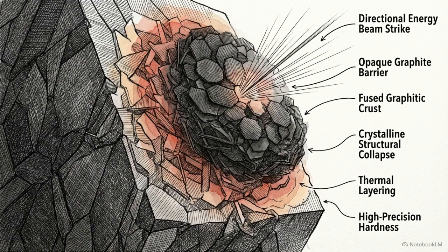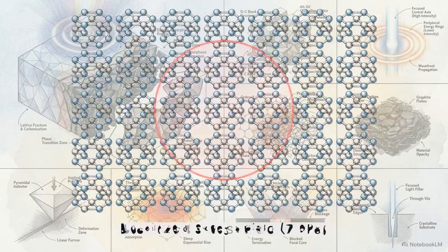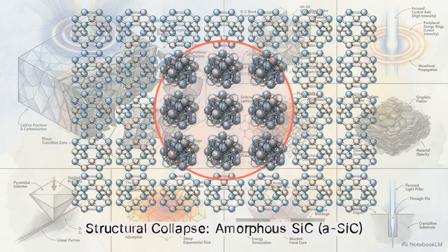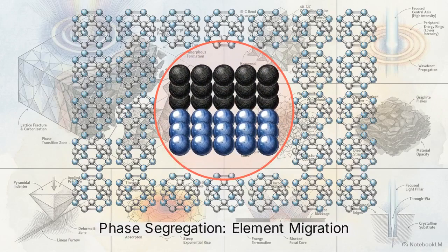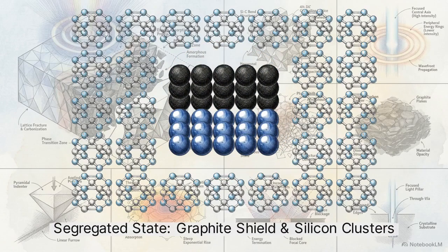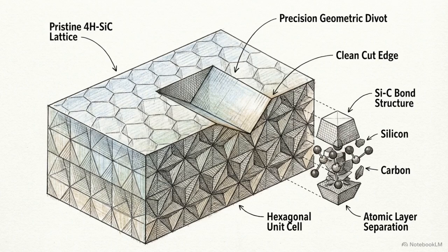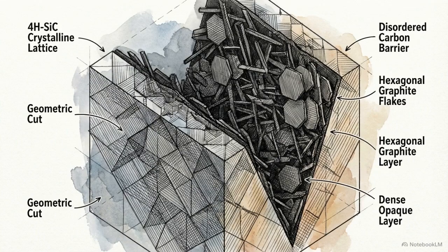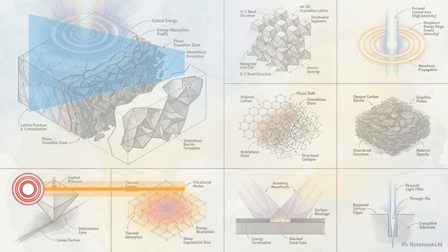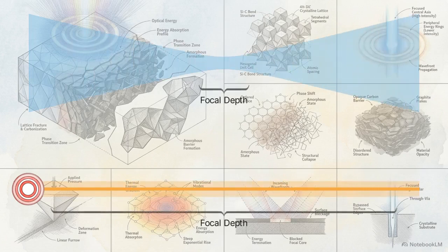This suggests the limitation is not merely the bulk hardness of the crystal, but a dynamic defense mechanism triggered by the manufacturing process itself. Under localized stress, the 4H SiC lattice undergoes phase segregation, altering its internal structure in real time. This segregation creates a localized shield. The material present at the start of the cut is physically and optically distinct from the material remaining at the end. The Bessel beam is theoretically the optimal optical tool for drilling deep vias because its non-diffracting core provides a massive focal depth.